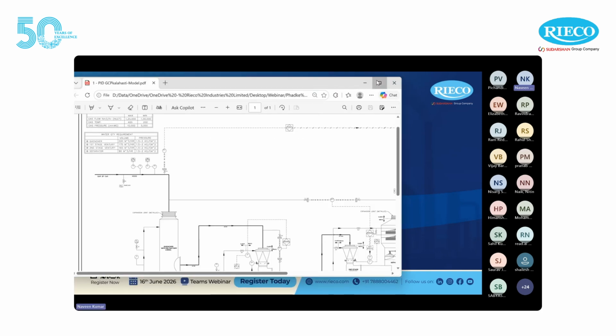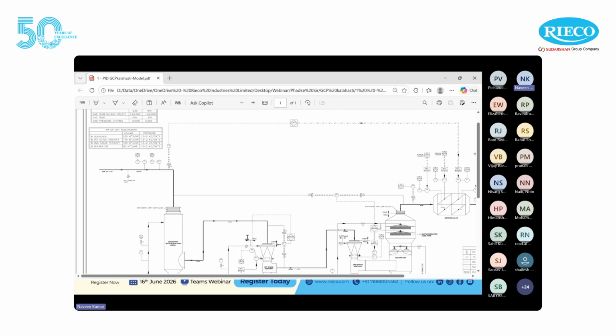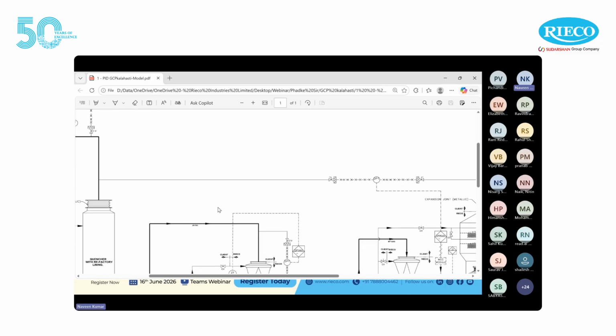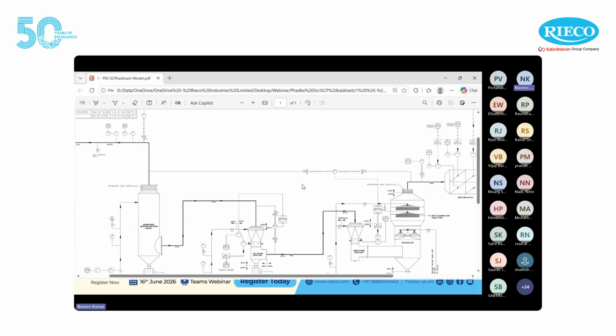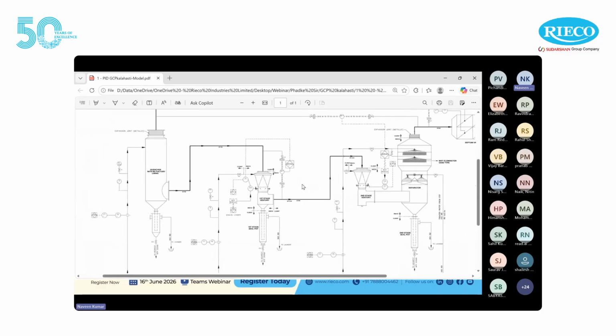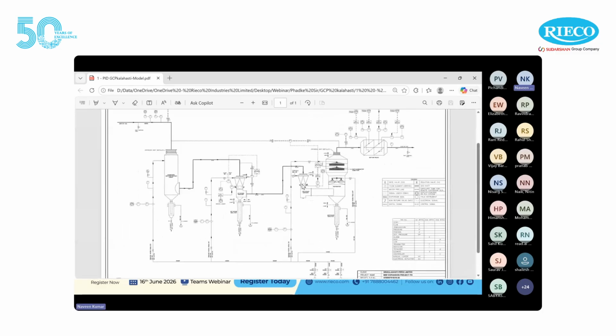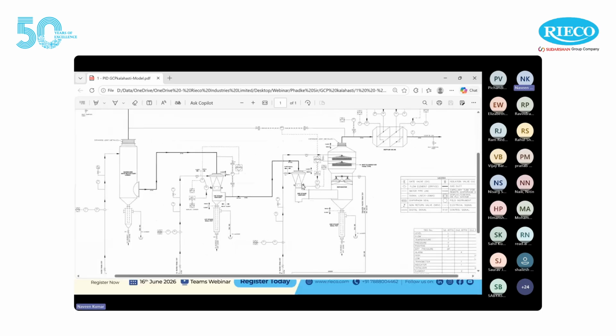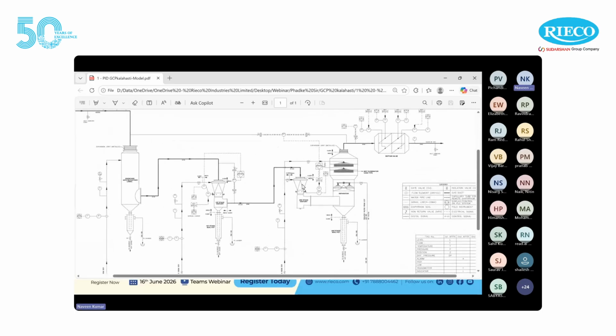The furnace volumes range from 100 to 500 meter cube with capacities of 100 to 1000 tons a day. Iron ore is reduced by carbon monoxide generated by coke combustion. We basically have inputs like iron ore or sinter, pellets, then coke, and fluxes like limestone and dolomite. These are introduced from the top of the furnace. And from the bottom, we have preheated air, sometimes even oxygen enrichment. What we get out of the furnace is hot metal, which is pig iron, some slag, and blast furnace gas.